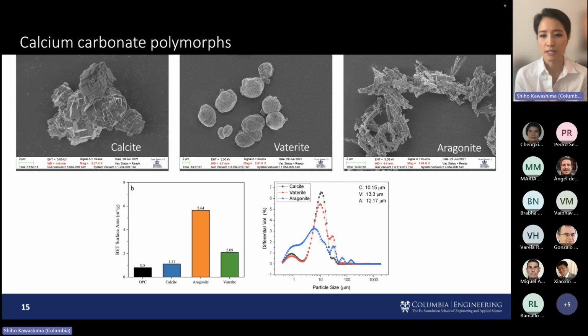And so some literature has already started to explore this, where aragonite has been found, because of its needle-like shape, to have reinforcing effects. And vaterite, because it's porous, the previous speaker mentioned internal curing. They may have the potential to absorb water and have internal curing capabilities. So what's exciting is that, again, these materials can start to add functionality. And our work has shown that these metastable polymorphs are actually stable in cement-based systems. So if we want to use vaterite as these porous spheres, they'll remain as porous spheres in the cement-based system. Aragonite will remain as needle-like materials.